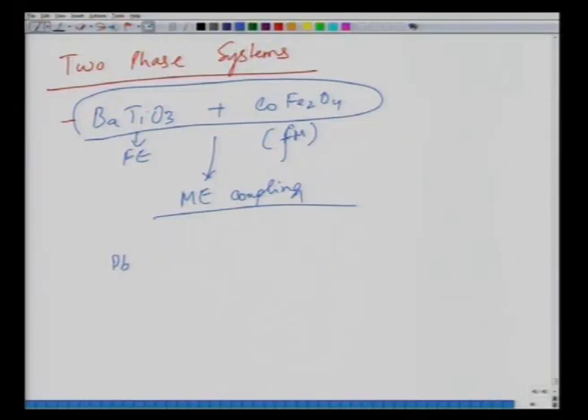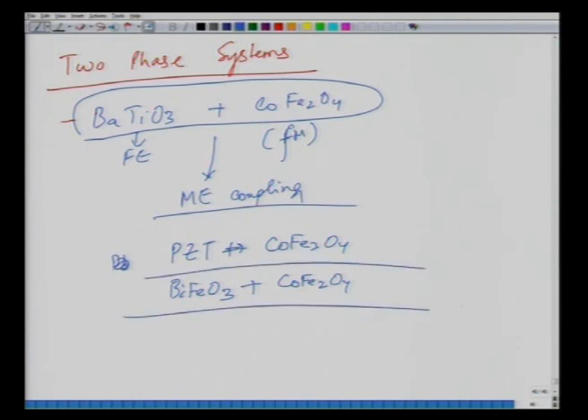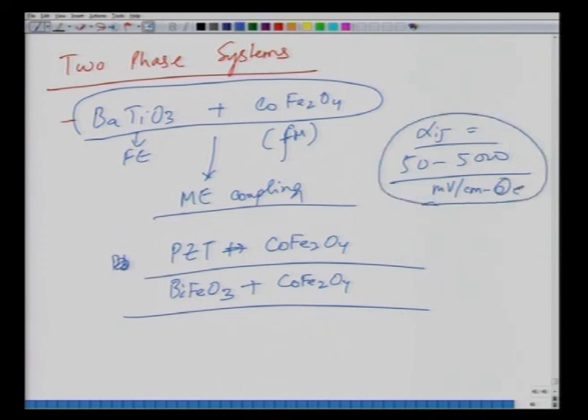And there are a variety of these materials: barium titanate, cobalt ferrite. You can have PZT plus CoFe2O4 and then BiFeO3 plus CoFe2O4. So variety of these structures are possible, and which have different coupling constants, and coupling constants vary from 50 to 5000. So you would say alpha ij. This would vary in millivolt per centimeter Oersted. So variety of these systems can be made artificially. So we'll stop. So this is the end of this module.